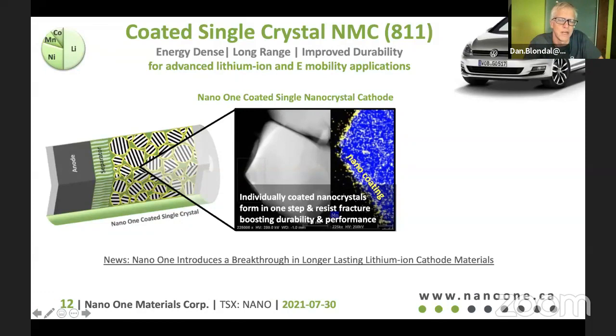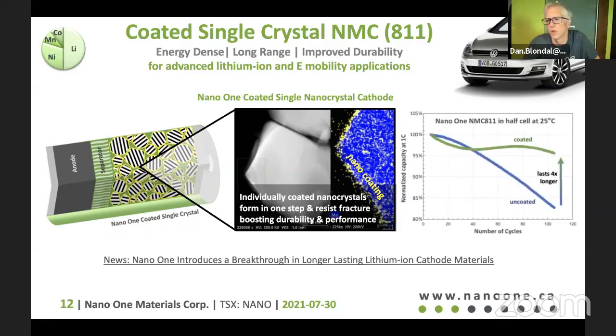That's the yellow image you see around the blue. And that provides a protective coating that allows lithium to go in and out really, really easily. But it prevents the nickel and manganese from reacting with the electrolytes and other chemicals inside the battery. And that leads to a longer lasting material. So you can see here, the green line is much flatter, the blue line is much steeper. And we're measuring here the capacity of the battery over a number of different charge cycles. So it just shows that there's a remarkable improvement in the longevity of the material when you add that coating.